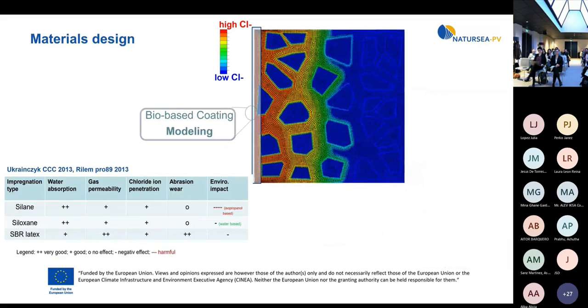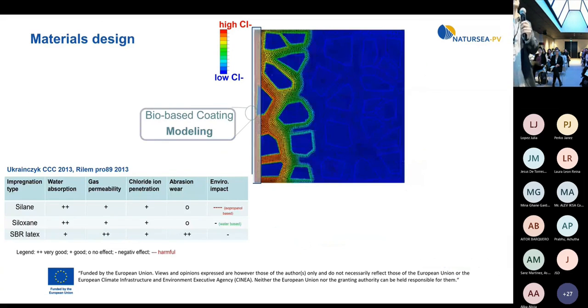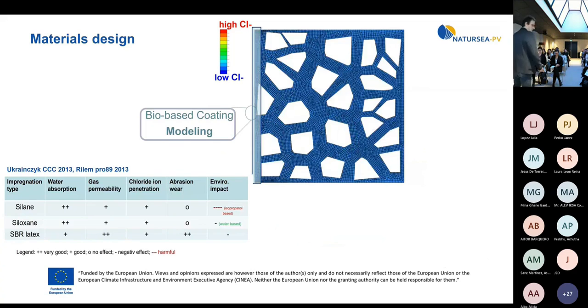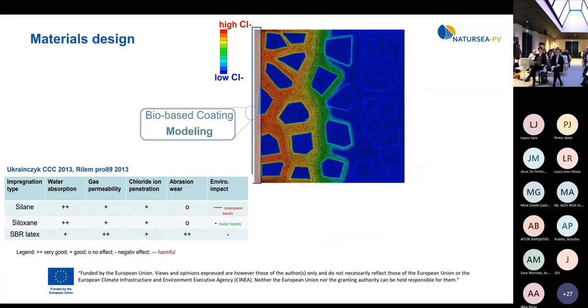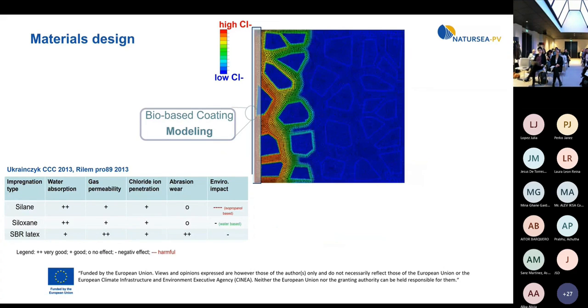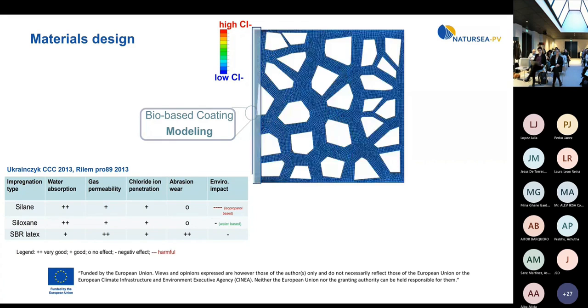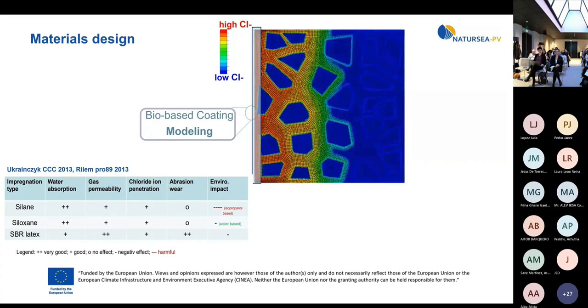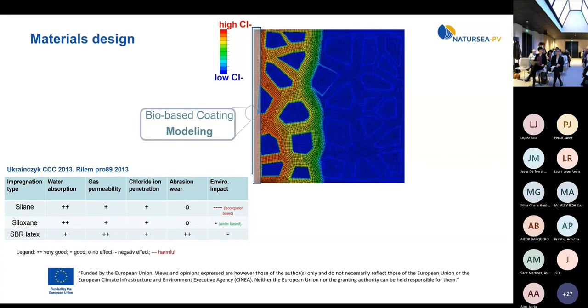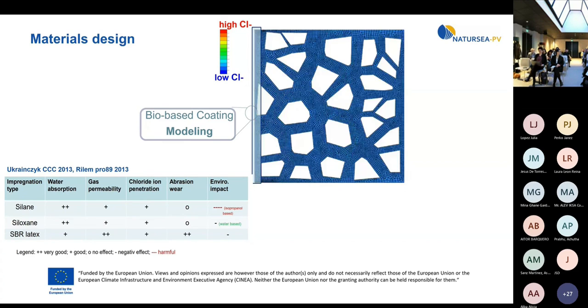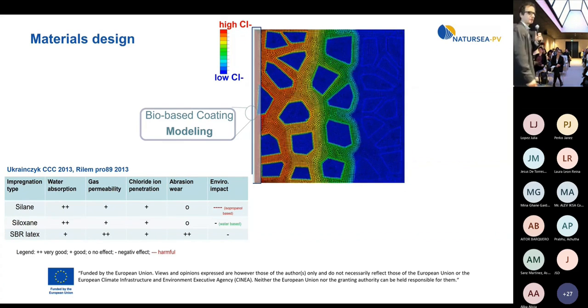And I did also some work in coatings, but we used styrene, but again latex, which is actually, I would even argue, not so sustainable. But in the US, they use it as a common solution for roads and bridges. When they have to remove the cover and repair, then they mix it with a certain percentage of latex or just spray it. So this is the coating.